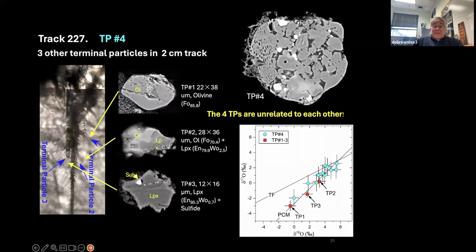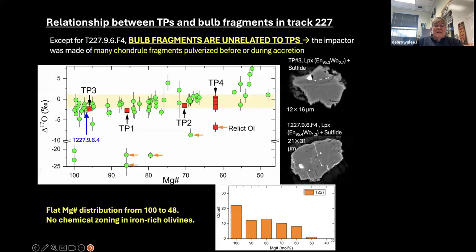They have different oxidized isotopic composition, different mineralogy, and different iron content of their olivine, as you can see in this next slide. So TP 1, 2, 3, and 4 — the horizontal axis here is the magnesium number, and you see they're really quite different, going from about FO 60 to FO 97 or so for TP3.